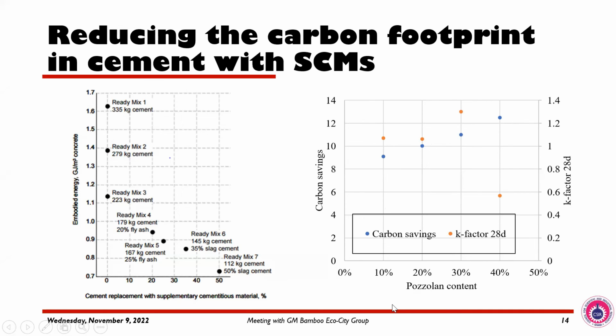Now, the efficiency factor is very key because you can have carbon savings and then at a point, your efficiency factor is not too good. So when you look at the orange dots, it is the efficiency factor. For example, if I look at 10%, I'm having efficiency factor above 1. Between 10 and 30, all the efficiency factors were above 1. But when I came to 40, the efficiency factor fell below 0.6.